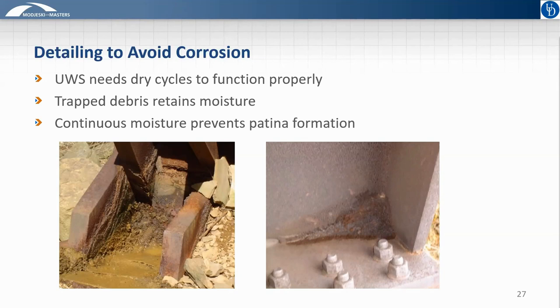So here we have a couple of pictures that show examples of this. On the left is a bearing assembly of, I believe, a truss bridge, where you can see that dirt and even mud has gotten in there. And that's going to prevent the water that collects there from ever drying out. You can kind of see in that image that you've already got layers of steel that have begun to peel off in corrosion. And on the right is an angle form that has collected debris, and you can see that the dark color of the debris kind of shows that it's collected moisture there, and it's not allowing that moisture to evaporate. And so the steel underneath that debris is continuing to corrode.